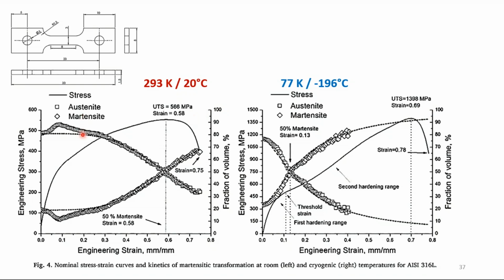And then, using the X-ray diffraction, we can see how these phases transform from austenite to martensite. And just for comparison, we have this point where the martensite is 50% and the strain is almost 60%. However, in low temperature, that same crossing point is going to happen at a strain of 0.13. There is much more information in the paper. I invite you to check those papers and see why this is happening. I'm not going to explain it here, but that's something that you can see while you are conducting the test.